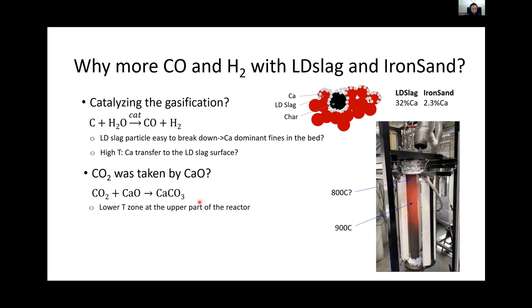Here is a picture of this reactor. In the main reaction zone or the bed zone, the temperature could not be low. It can be 850 to 950. That's what we want. So the carbonation cannot happen at such high temperature, based on our thermodynamics calculation. But on the upper part of the reactor, the temperature could be lower than 800 degrees. But at this lower temperature, this carbonation can happen.